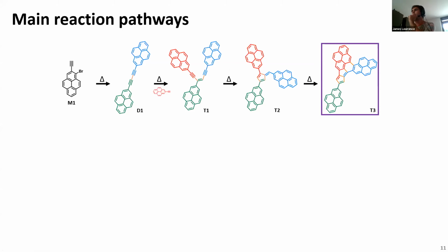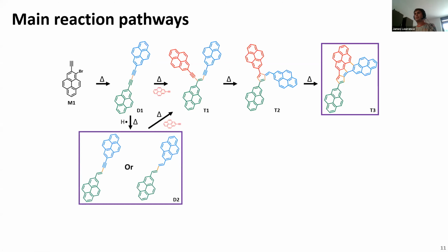Now, of course, we also form these double bonded forms of the dimer, which can also potentially go on to form this trimer and continue this reaction as well. But mainly with this system, we only see these at higher temperatures. So if they do form this, they transition very quickly to form these trimers.